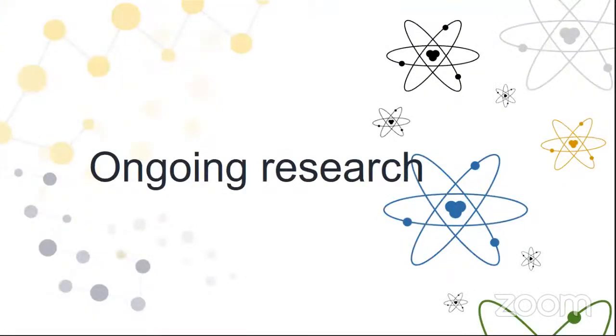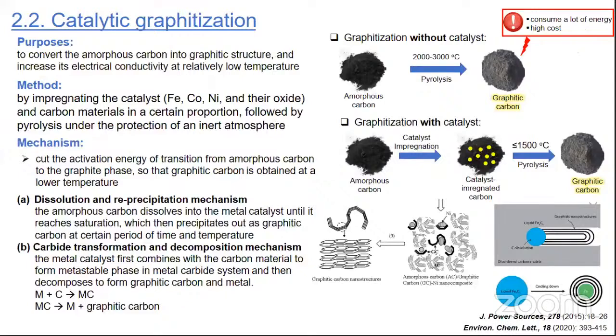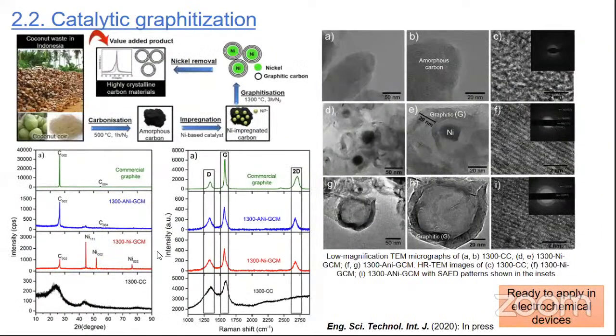Okay, this is our ongoing research. As I mentioned before, the properties of our CCP still have low conductivity. So we conduct some treatment to improve the electrical conductivity using catalytic graphitization to convert the amorphous carbon into graphitic structure. And this is our publication. We are successful to convert the amorphous structure to graphitic structure and improve the electrical conductivity.